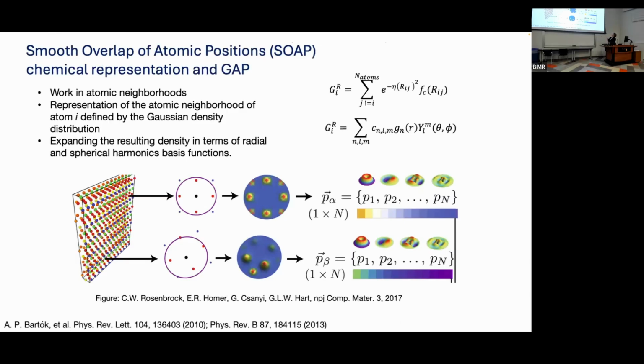In this case, you still have these Gaussians placed on the bond distances within some cutoff radius. You first define the radius, place the Gaussians, and construct this local representation, and then you can pass that through some filter, in this case a spherical harmonics filter, that gives you the rotationally invariant representation. So this now has knowledge of how, when you rotate your molecule, it will behave in 3D space.